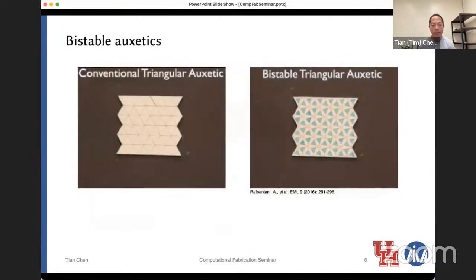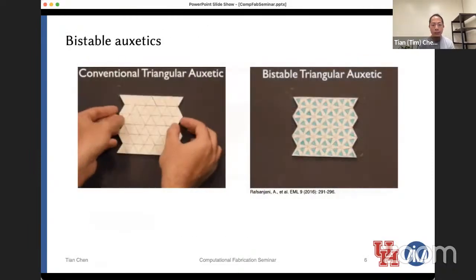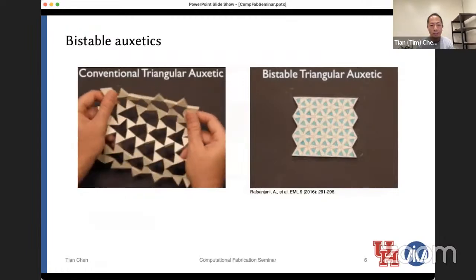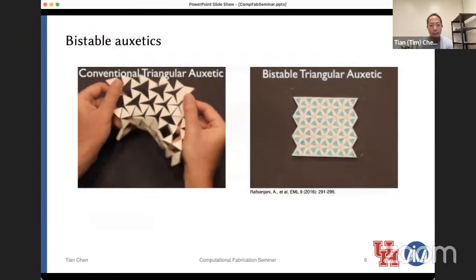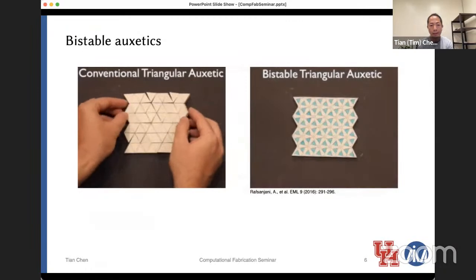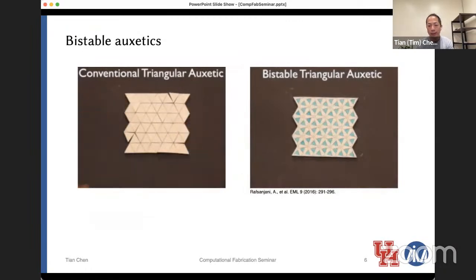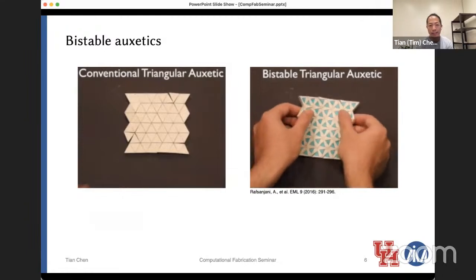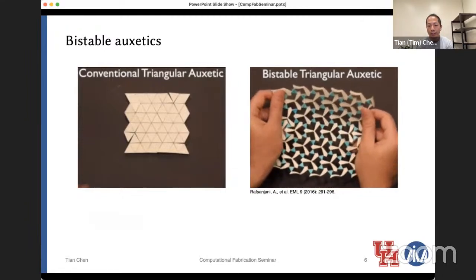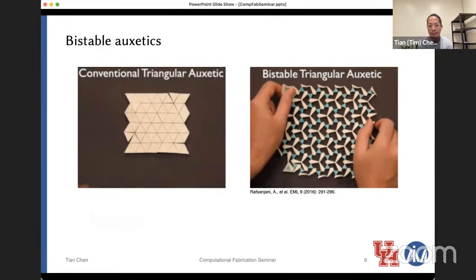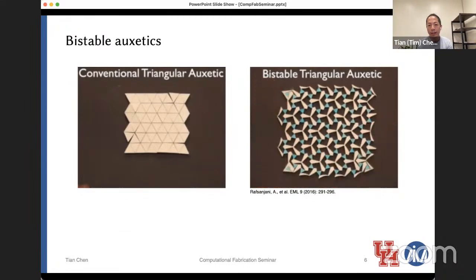And with bistable auxetics, we pretty much have seen this already. So with a regular linkage, you can expand to a factor of 2 in length. Yet with the bistable triangular auxetics, even though the base material is exactly the same, it's a rubber sheet, when you expand this, it stays expanded. And you have to apply mechanical force to have it go back to the original state. But of course, because the expansion ratio is the same everywhere, you just get a bigger sheet.